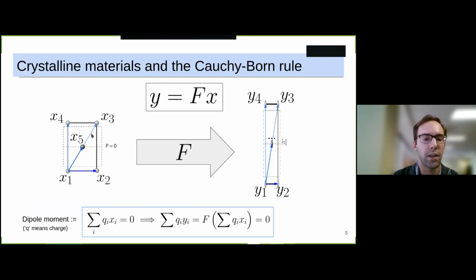If we have a crystalline lattice, we maybe have some particles that are arranged in a lattice that are weakly ionic. They have some net positive or negative charge. Now if we think about relating the deformation gradient at a material point to how the lattice vectors are changing under that deformation, what's very often used is what's called the Cauchy-Born rule, which is essentially that each of the lattice vectors is mapped under the deformation gradient. What you see when you do this is that you need to have a strain gradient. As long as you have a vanishing dipole moment in the reference configuration, you will always have a vanishing dipole moment in the deformed configuration as long as your deformation is homogeneous.